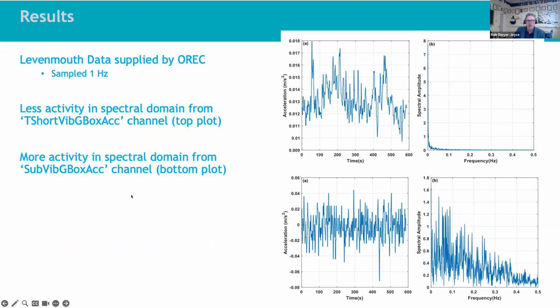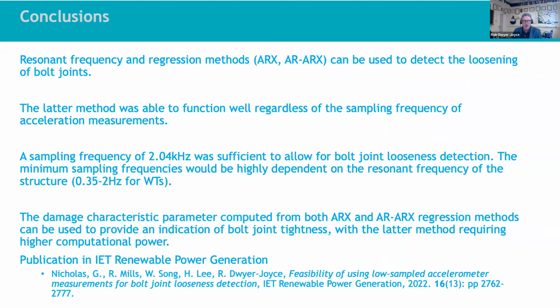And then the aspirational goal is what can we do with recorded data. So this is not really results, it's a challenge. This is data supplied by OREC, which is vibration sensors already on the turbine, and you can see that there are two sets of data and two very different sets of data, and we haven't yet, but the frequency is too low. This is only sampled at 1 hertz, and so we couldn't predict at this low frequency. But the trick is now to see if we can find alternative methods to either sample this data or use higher frequency sampled data.